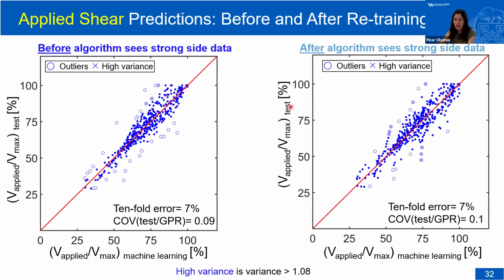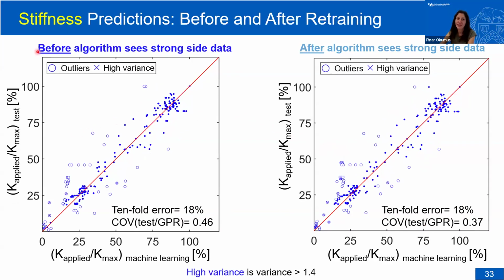All right, next is our applied shear predictions. Applied shear predictions look like this before. It was already pretty good, 7% error and less than 10% coefficient of variation. It didn't change much. I don't think you could get better than this with a data-based approach. And then finally, our stiffness predictions again. We had that large scatter. We still have that large scatter, but our coefficient of variation is a little bit better. So we're happy with that outcome.